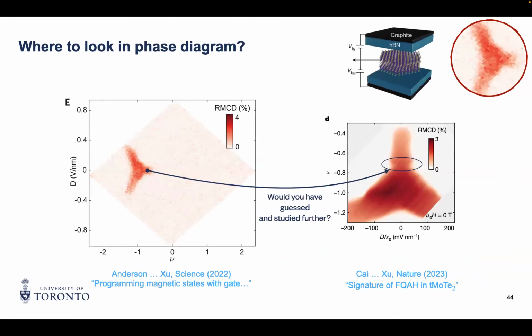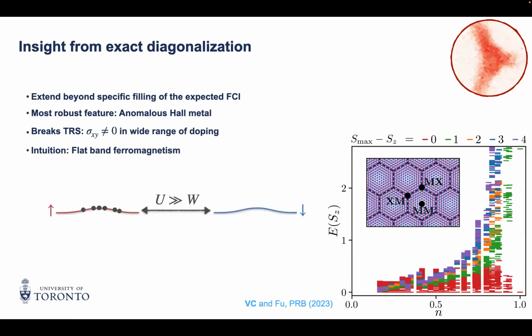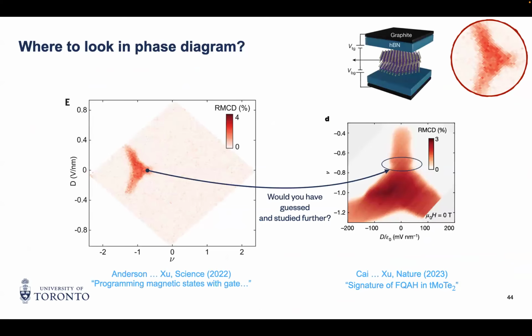I took too long. So let me just say something else, which is precisely what I just said. So this is twisted MoTe2, which we predict, like our table says, it has a topological band gap of about 10 Kelvin. And that's indeed what has been seen. So the state at nu = 1 here is a ferromagnet. It lives in a band with Chern number 1. And when people did transport, they indeed saw the sigma xy quantized in units of e²/h, right? With no longitudinal resistivity. So that match, at least we were happy our data match what they found.